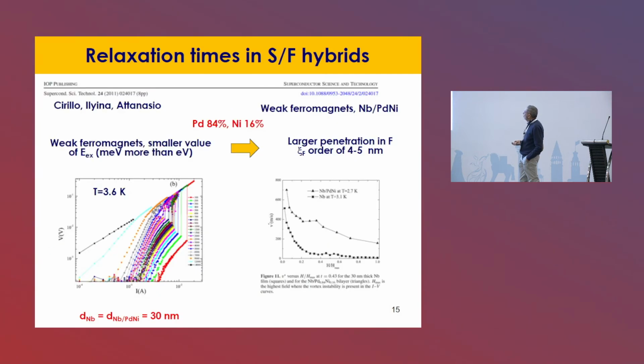I will not go into details. We studied a lot of other materials. Now we pass to weak ferromagnets, niobium palladium nickel. For example, here is the critical velocity for niobium, and here is for niobium palladium nickel. And again, an increase of the critical velocity. All these samples are always prepared in the same deposition run. So the quality of niobium here is exactly the same as here. And you see, higher critical velocity.